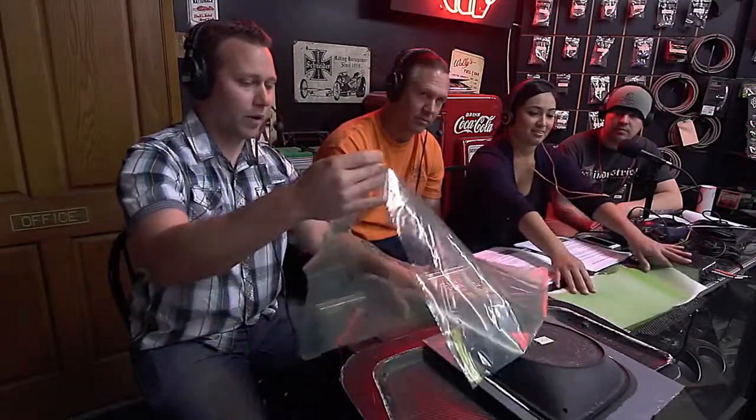So you can either tape down on top of the mold if it's got a lip, or depending on what it is, you can use an envelope bag like this. This is just a nice little clipping of it. Take your whole mold, your part, everything, throw it inside, and then you're going to tape it up, seal it up, use a spiral on the inside with some outlets, and then you're just going to vacuum that thing down. So you got to have a vacuum on this. Okay. And what that's going to do is it's just going to press everything together. You've got an outlet on one side going to your vacuum, and then the other side goes to your resin. Turn the vacuum on, let all that resin suck through the top side, suck through the part, and then out the back side. Clamp it off, let it cure, and then when you're done, take it out of the oven, peel your stuff off. There's your part.